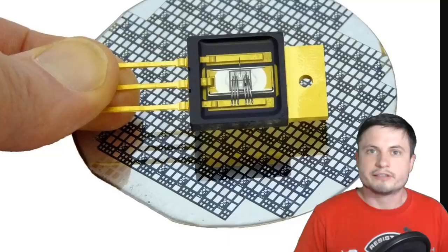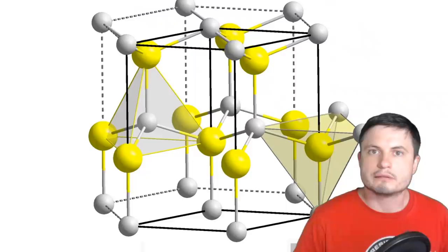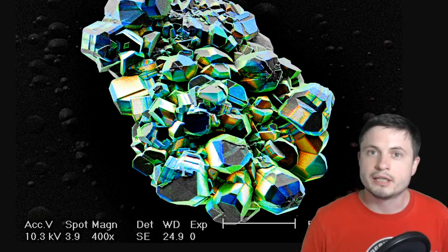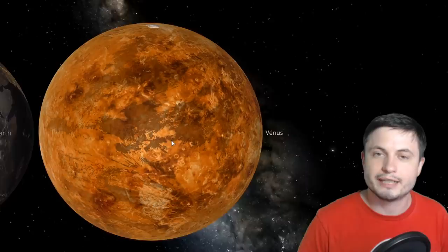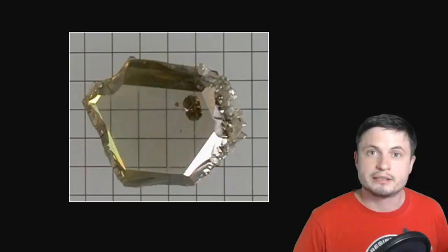One of the solutions is to try to use some other material, like silicon carbide or gallium nitride, to produce electronics that can survive at higher temperatures. Gallium nitride, for example, can survive up to around 400°C, but Venus is even more extreme than that. So even though these electronics might survive on Venus a little bit longer — potentially enabling missions that are days long instead of hours — we're still very early in the development of these technologies. Only studies from 2020 were able to create stable gallium nitride electronic devices, which are still extremely primitive for what NASA needs. For now, electronics are out of the question on Venus.